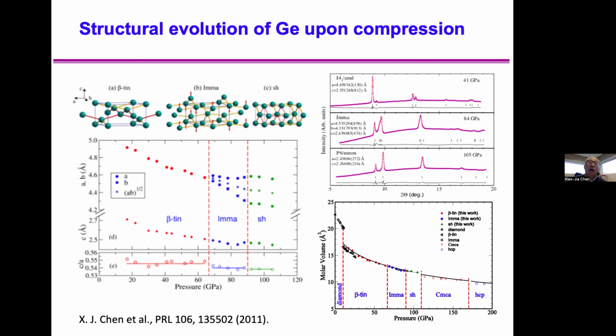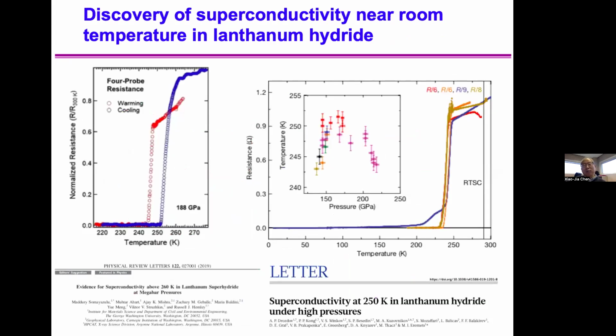That's why we investigated the structural changes with pressure. At that time, the structure evolution of germanium was not well defined, so we used this idea for that. We established the equation of state and the structure evolution of germanium with pressure. That work was published in 2011. Here, I would like to mention the great breakthrough that came from the group of Professor Ma. That's Zhu Lu, the first author of the paper they published in 2019.